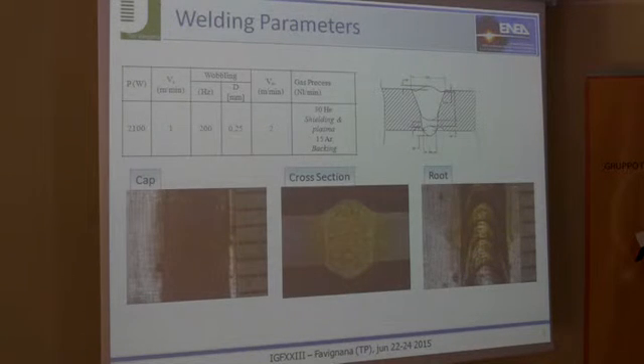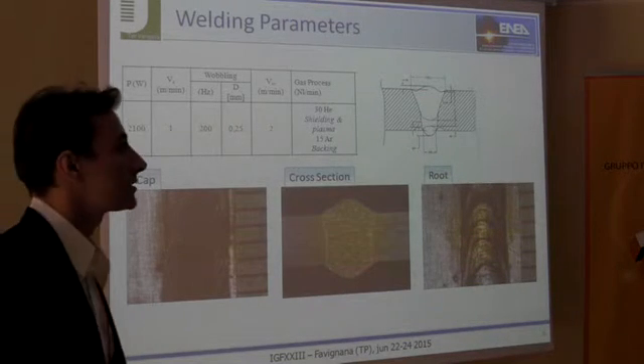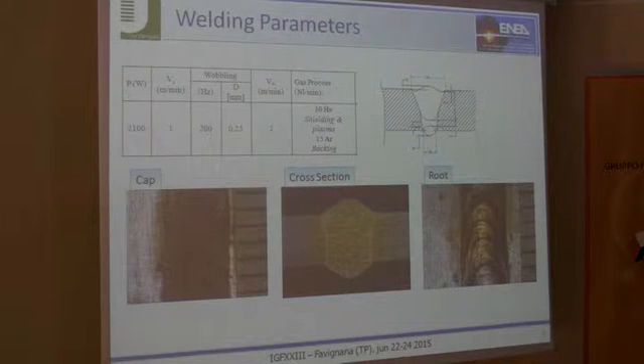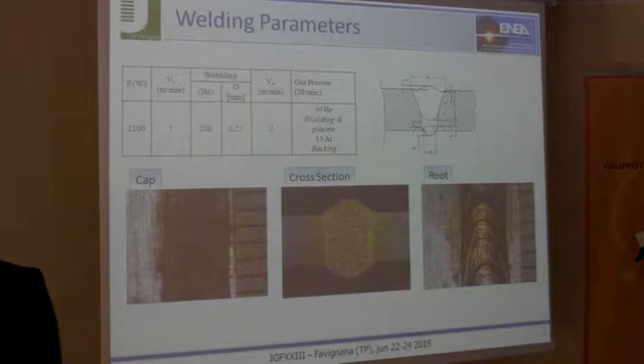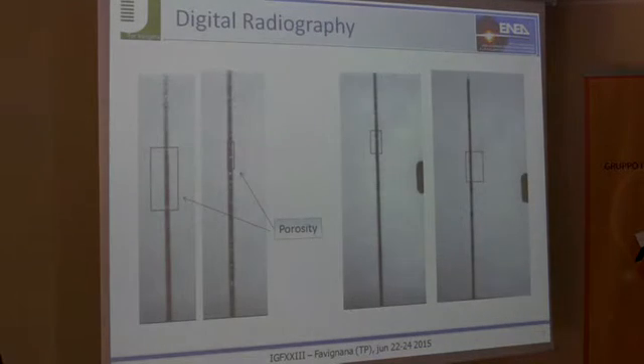For the identification of the best welding parameters, a series of preliminary tests was performed, and the target was to realize welds in compliance with level B of the EN 13919. And we investigated a very large number of parameters, but the most important were the diameter and the frequency of the wobble and the welding speed. As a function of these, we analyzed the cross section of the welds and the porosity of the welds.